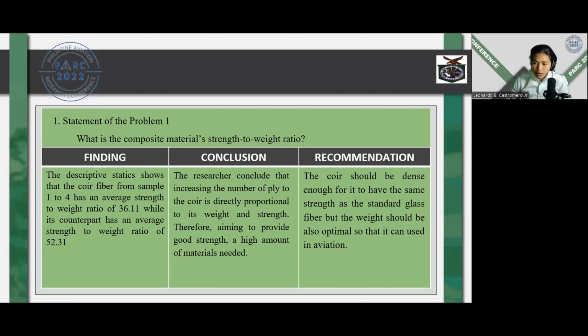52.31. Conclusion. The researchers concluded that increasing the amount of coir is directly proportional to its weight and strength. Therefore, to provide good strength, a high amount of material is needed. Recommendation. The coir should be dense enough for it to have the same strength as the standard glass fiber, but the weight should also be optimal so that it can be used in aviation.